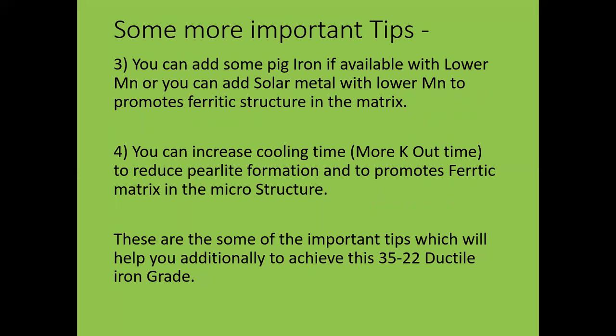Next tip is you can add some pig iron if available with lower manganese, or you can add solar metal with lower manganese to promote ferritic structure in the matrix. Another tip is you can increase cooling time, that is more knockout time, to reduce pearlitic formation and to promote ferritic structure or ferritic matrix in the microstructure. So these are some of the important tips which can be used for achieving the results for this grade of 35 by 22, which will help you to additionally achieve this 35 by 22 ductile grade.